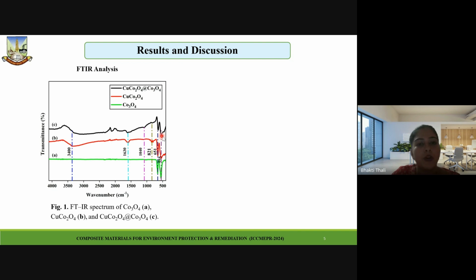In the final copper cobaltite cobalt oxide nanocomposite, the peaks which were present in copper cobaltite and cobalt oxide are also present in the final nanocomposite. In addition to this, there were two peaks seen at 821 and 1040 cm inverse, which indicate that a facile interaction has taken place between cobalt oxide and copper cobaltite. Thus, the synthesis of the copper cobaltite cobalt oxide nanocomposite was successfully confirmed by FTIR.